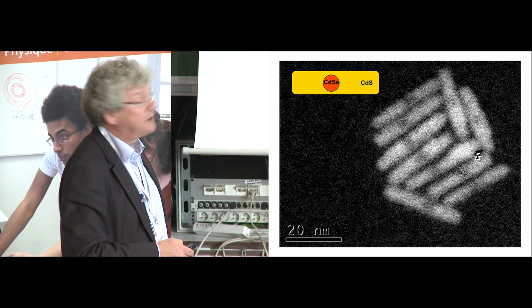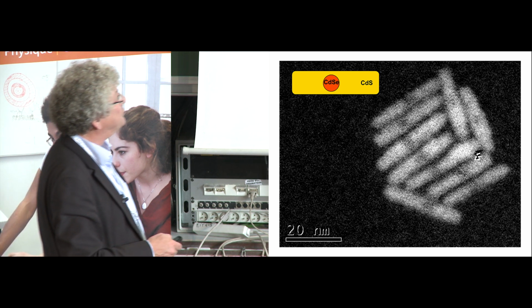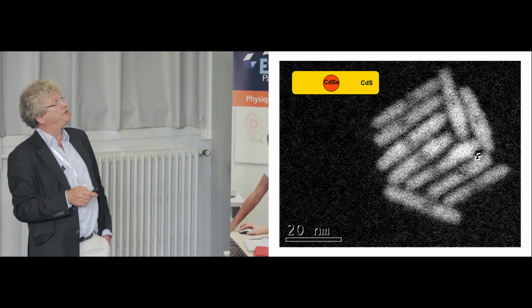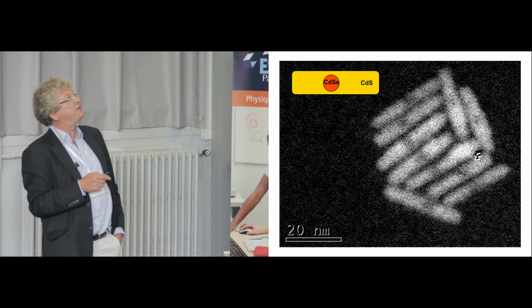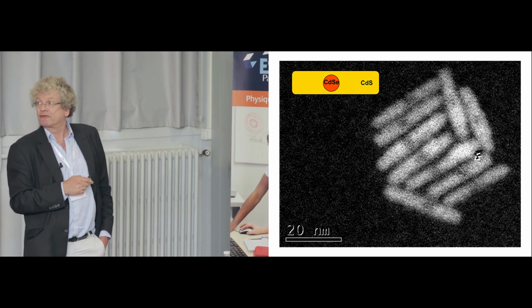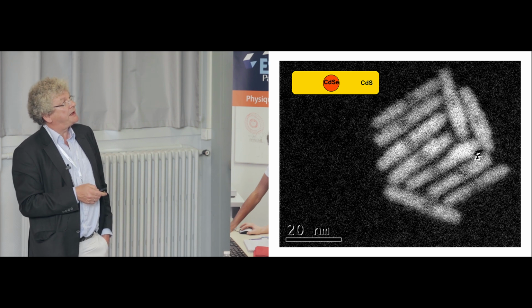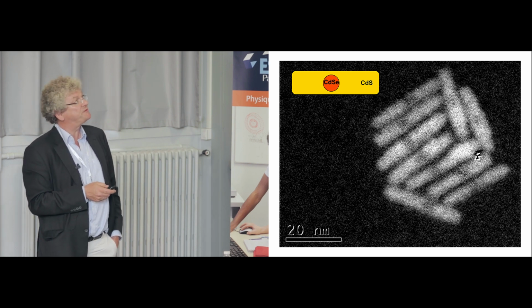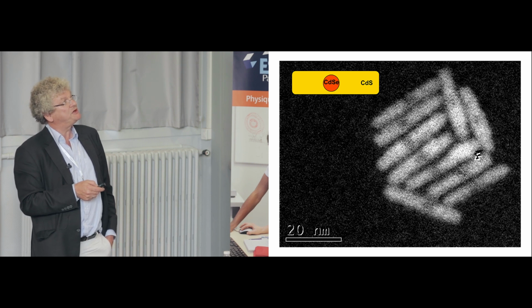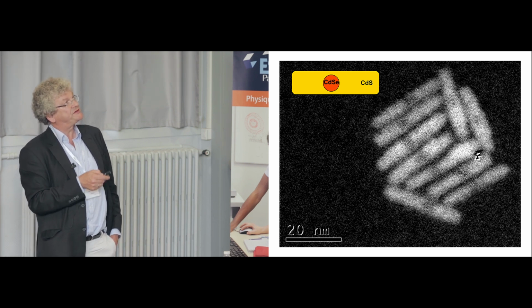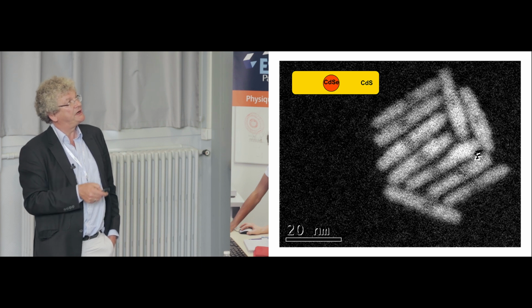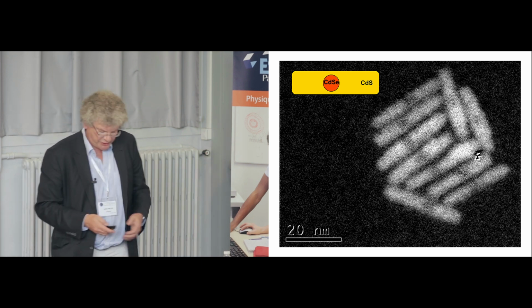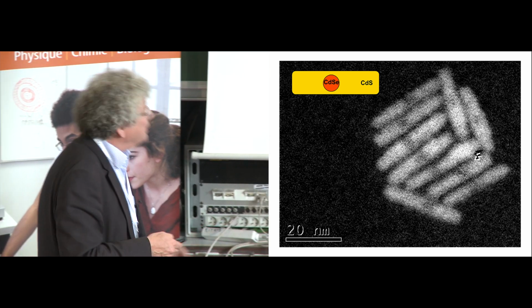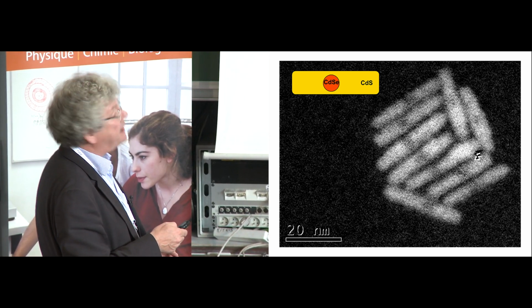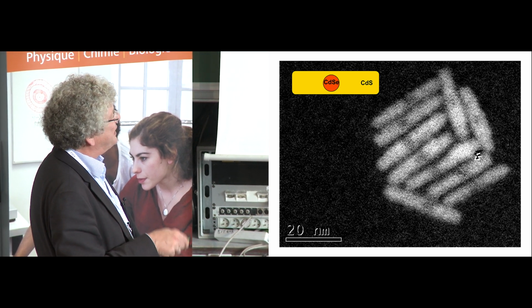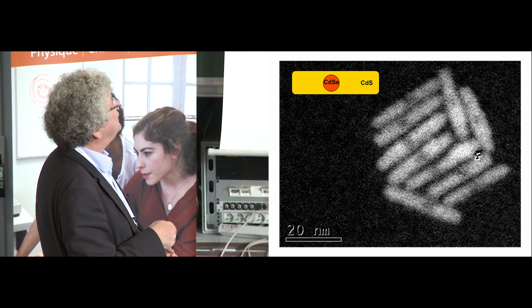Interesting things, and I think you will hear more about these in further talks, for example, by Uri, are these dot rods, quantum rods, with an unidirectional growth of a shell, like here. And you can see also with these new microscopes very nicely, if you use energy-filtered imaging, here is the core, and this is the shell. So we have them here in the middle is the cadmium selenide core. Other things like EDX analysis, you can make line scans and you see where is the cadmium selenide in the center and the sulfide at the outside.